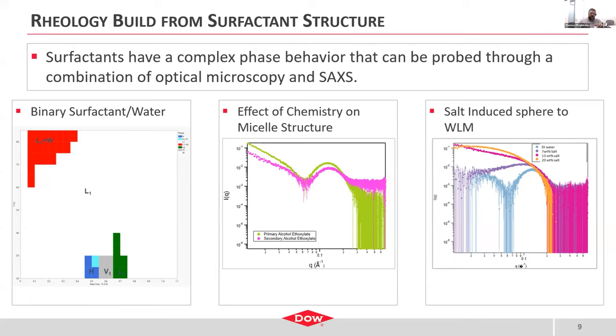In the primary alcohol ethoxylate, the bonding happens through an ether bond on the end of the hydrocarbon. On the secondary alcohol ethoxylate, it's happening somewhere else along the hydrocarbon chain, while the oxygen is in the secondary position. And what you can see is in the primary alcohol phase, you get a small angle scattering pattern that is consistent with a spherical micelle. However, when you go into the secondary alcohol ethoxylate phase, the micelle actually changes shape slightly into an elliptical micelle. So by changing the chemistry of the surfactant, we can change the self-assembly structure present.